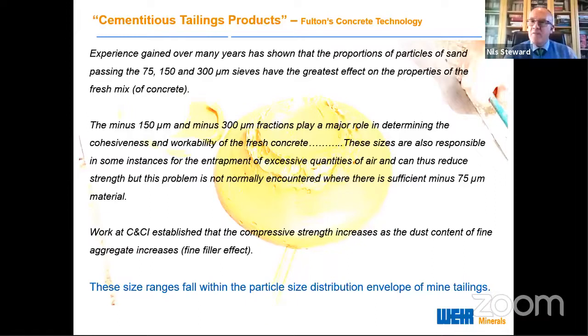But if you have less than 75 micron material in it, it actually prevents that air entrainment. We obviously have lots of minus 75 micron. And one of the other things that Fulton notes is that an increase in dust component, which is minus 75 microns, actually lends itself to strength. And all of these are part of our mine tailings.